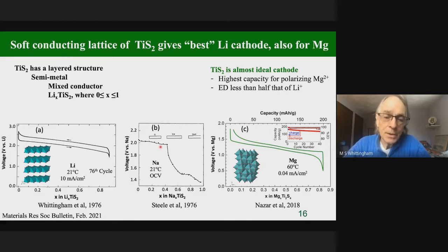So we can get sodium ions in there. The structure is much more complex with sodium because it's a bigger ion, so it actually has to separate the layers to get in there. So we get these different phases. And doubly charged ions like magnesium can also go into the lattice.